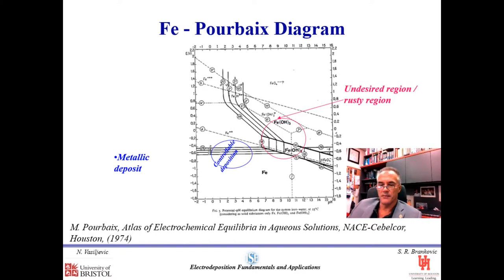In relation to the certain range of the current density that we want to choose, for certain metals we want to also be aware, when we design the solution, that the pH range where the solution should be designed is very much dependent on the stability of the metal ions in the solution, and some metal ions are prone to form hydroxides, which are insoluble, and then stability of your solution, like for example here iron, is something that might be an issue.